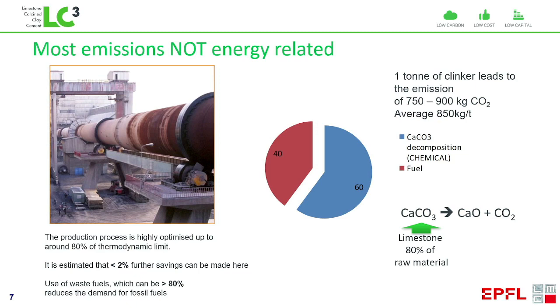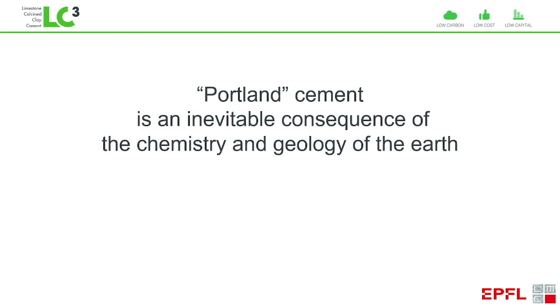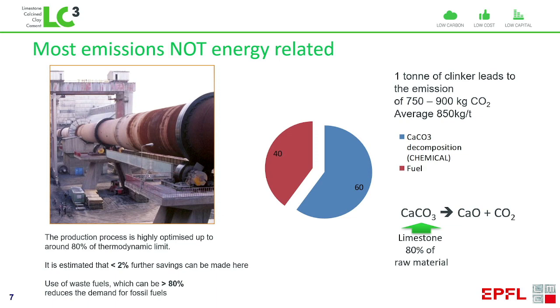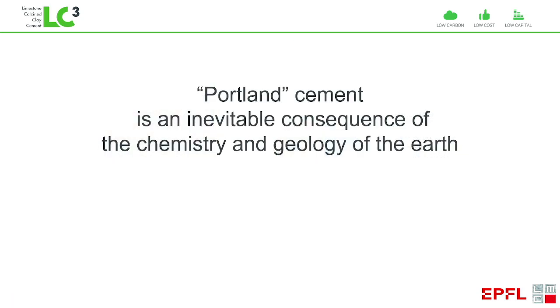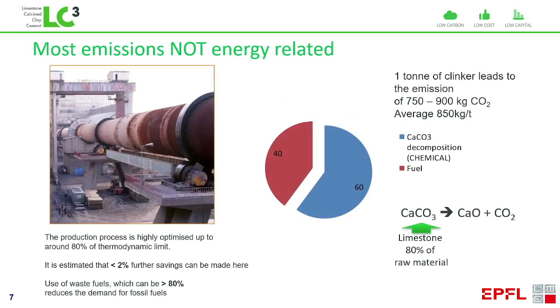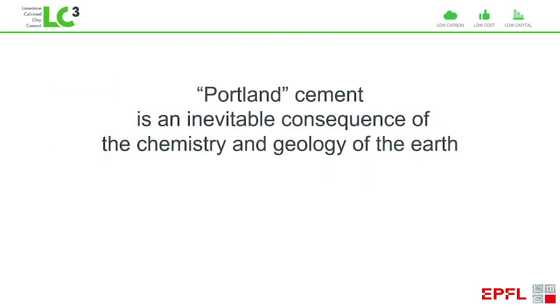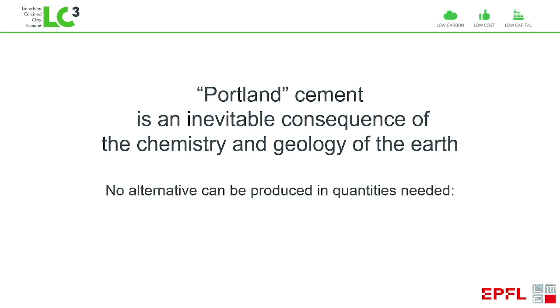The other issue we are facing with cement is the origin of the CO2 emissions, which are coming from more than half of the emissions, about 60%, are coming from this simple chemical equation, which is the breakdown of limestone, 80% of the raw material, into calcium oxide and CO2. Now, this material we call Portland cement. We cannot really come with alternatives because the chemistry and geology of the earth means it's the only material we can produce on the scale needed.